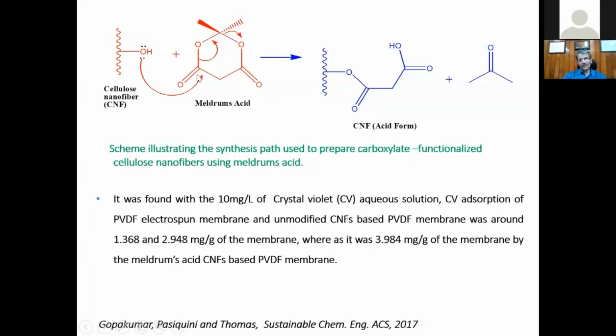This is nanocellulose. We reacted it with Meldrum's acid, the green chemistry, and you can see negative groups on the surface, COO minus groups on the surface of nanocellulose. Very interesting green chemistry. And if you do that, look at the efficiency of the separation process. This is a commercial filter you get in the market. Removal of crystal violet dye, you can see adsorption capacity as a function of time. This is after coating with nanocellulose on the surface of the commercial filter. The top one is chemically modified nanocellulose. You see the separation efficiency is quite good.